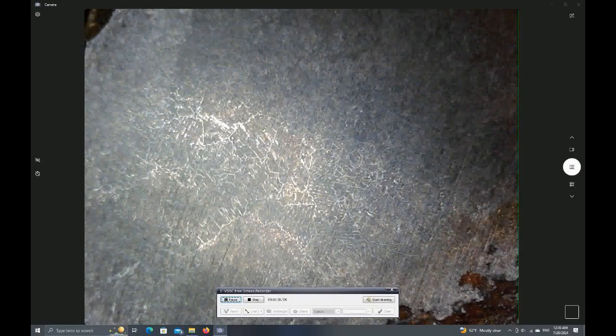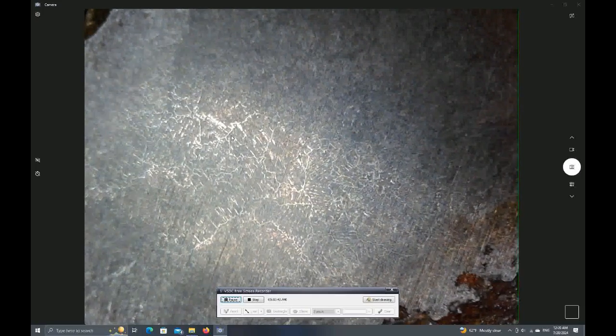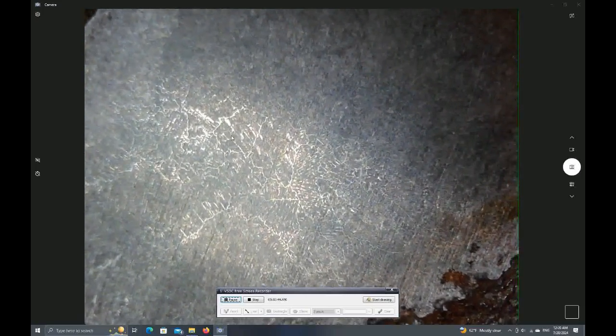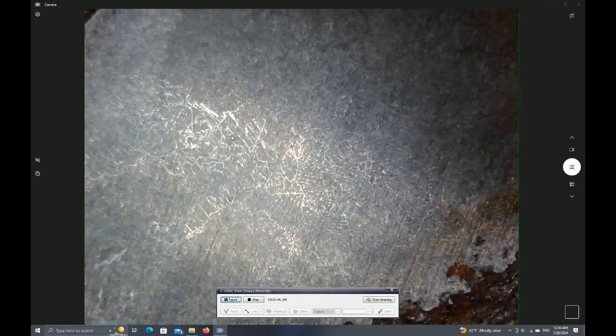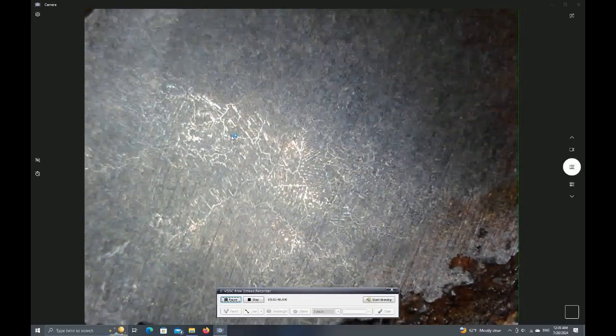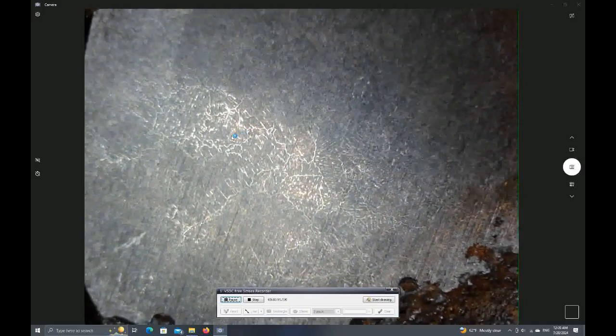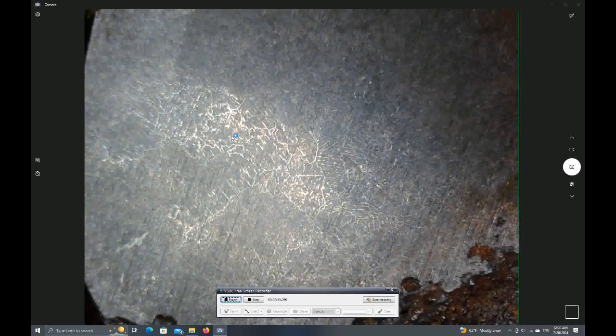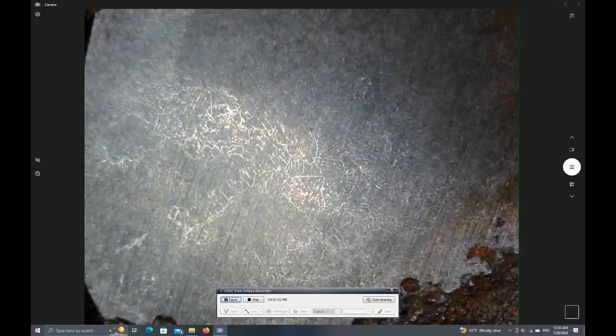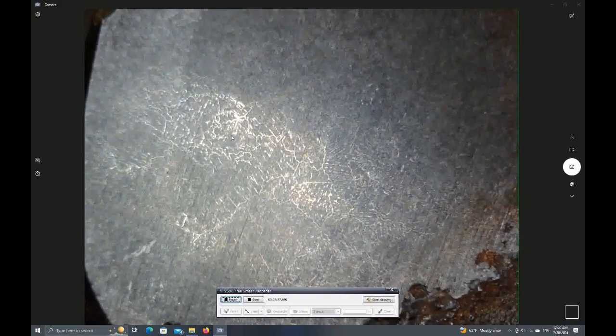So if I get this too hot, those are all going to just turn into points where the ingot's just going to crumble like a cookie. So I would probably be really wise to roast this ingot at something like 1800 degrees Fahrenheit for, I don't know, a couple hours before I start hammering away on it.